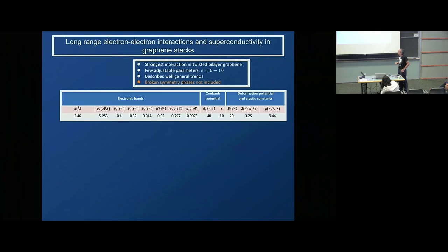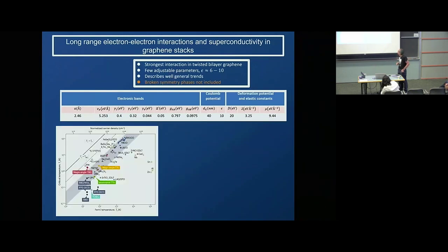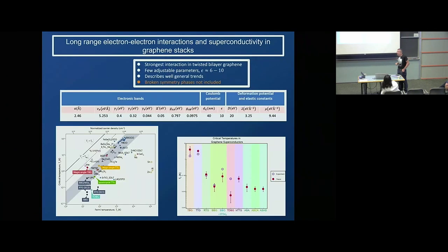We have used always the same set of parameters for all the systems, and these parameters existed before twisted bilayers and so on. They are well known for graphene work. So I think the trend we get for the superconductivity is quite reasonable. Of course, when we get very, very low critical temperatures, it means that this mechanism is very weak, and then any other mechanism may change things significantly. That cannot be ruled out, but at least the fact that there is a big difference between twisted bilayer graphene and the other superconductors is there.